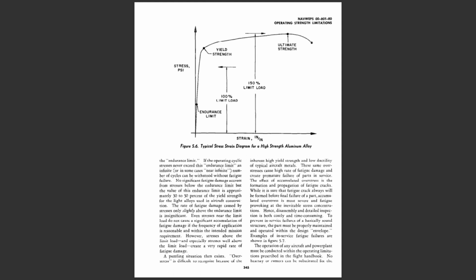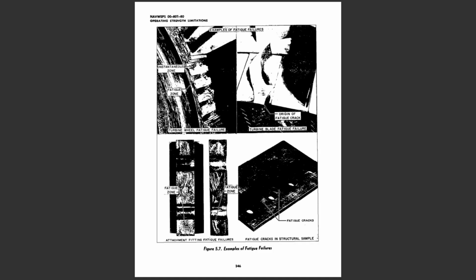Overstress is difficult to recognize because of the inherent high yield strength and low ductility of typical aircraft metals. These same overstresses cause high rate of fatigue damage and create premature failure of parts in service. The effect of accumulated overstress is the formation and propagation of fatigue cracks. While it is sure that a fatigue crack will always be formed before final failure of a part, accumulated overstress is most severe and fatigue-provoking at the inevitable stress concentrations. Hence, disassembly and detailed inspection is both costly and time-consuming. To prevent in-service failures of a basically sound structure, the part must be properly maintained and operated within the design envelope. Examples of in-service fatigue failures are shown in Figure 5.7.